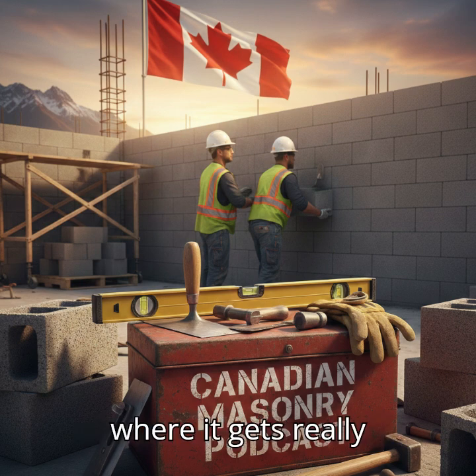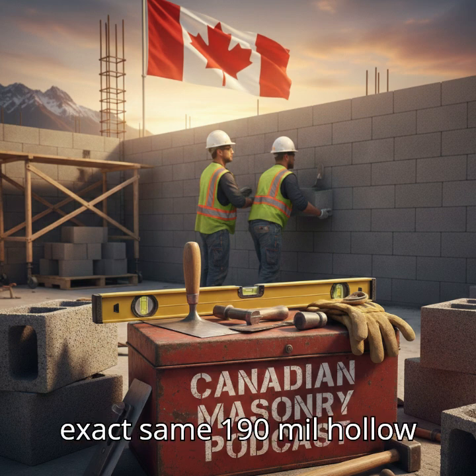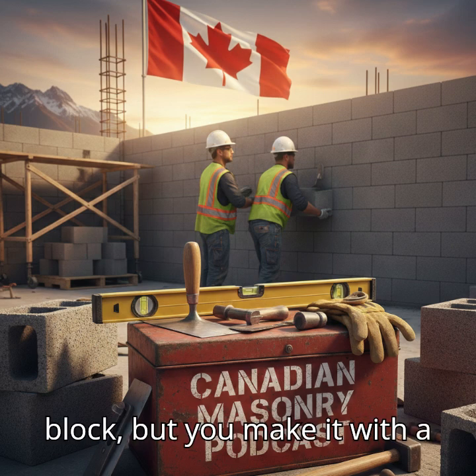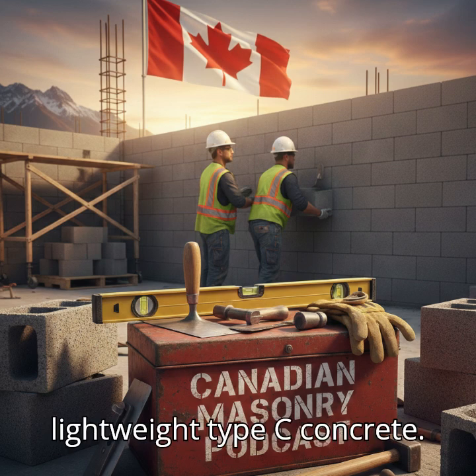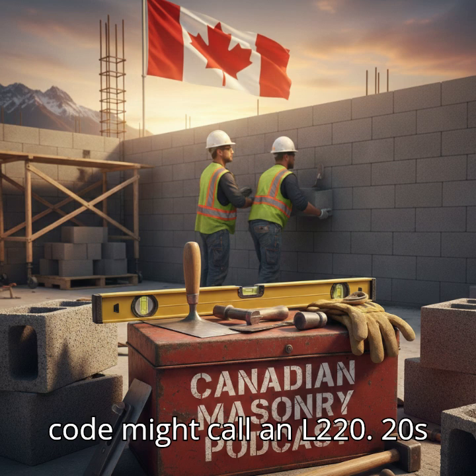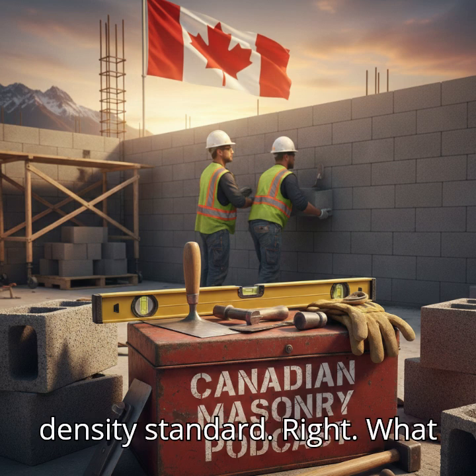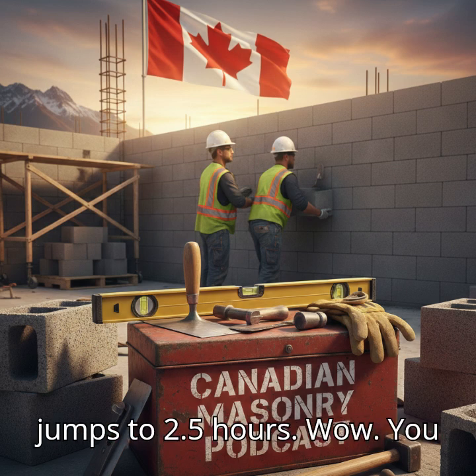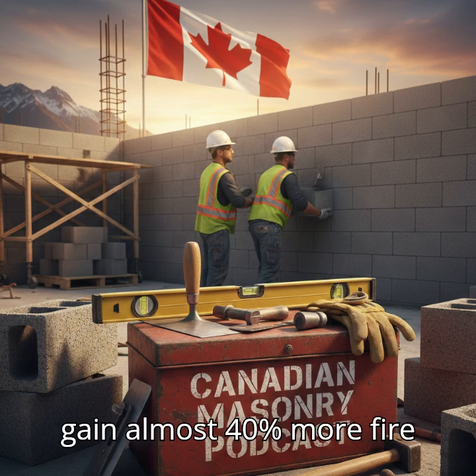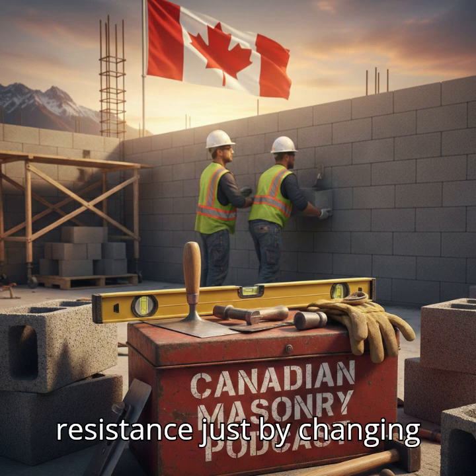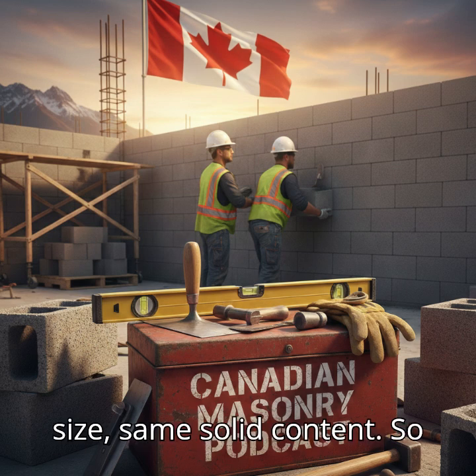But this is where it gets really interesting. You take that exact same 190 mm hollow block, but you make it with a lightweight Type C concrete. Or what the National Building Code might call an L2/20S density standard. Right. What happens to the rating? It jumps to 2.5 hours. Wow. You gain almost 40% more fire resistance just by changing the aggregate type. Same size, same solid content.